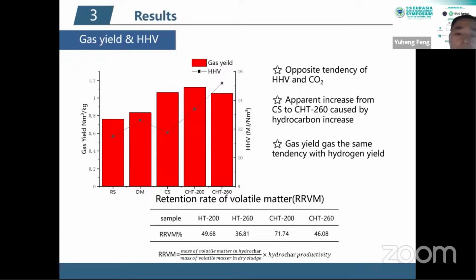Also, when we check the retention rate of the volatile matter, we could find that with the calcium oxide condition, the volatile matter retention is largely increased by the addition of calcium oxide. This is because of the retention of some fatty acids by the calcium oxide. Also, if we raise the hydrothermal temperature, the retention rate will be reduced, which is also the reason for the gas yield reduction.